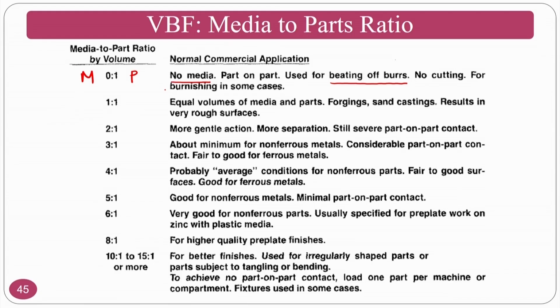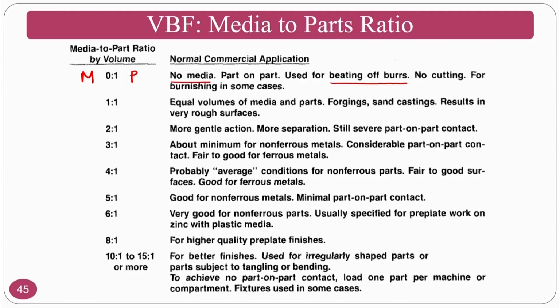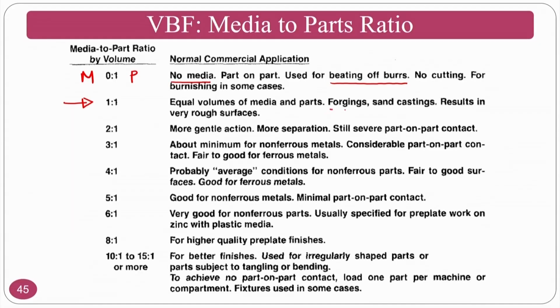If I want to get a burnishing operation on top of a workpiece, then you have to go for 0:1. If I want to go for 1:1, that means 50% abrasive particles and 50% workpiece components, equal volumes of media and parts, and this results in very rough surfaces. So in these circumstances, the abrasive particles will generate very rough surfaces.